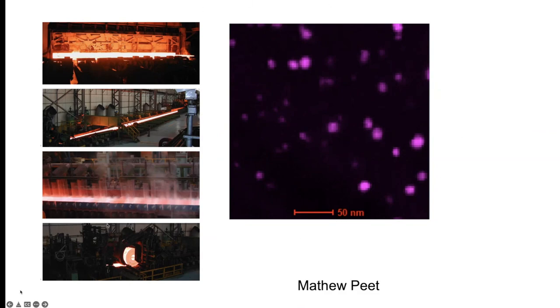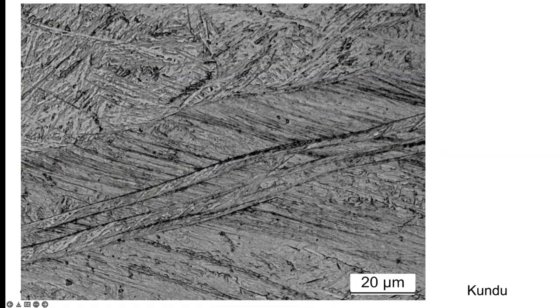Now, this is a particular steel that we developed, which is fully martensitic, and we wanted to create an austenite grain size which is about 0.4 micrometers in size. You can only do that if you pancake the austenite grains, you squash them, and you add a microalloying addition which is stable at low temperatures, because niobium, for example, is used when you hot deform at high temperatures, something like 1200, 1100 degrees centigrade. Here, we wanted to get down to 800 degrees centigrade, and niobium would not be any good because it precipitates out at high temperatures. So this is a vanadium microalloyed steel. And here is the structure, very, very pancaked grains of austenite, okay?